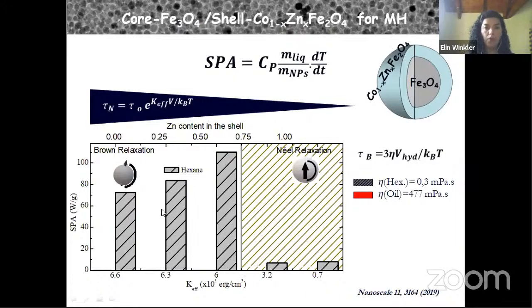So how can we prove that the heating of these three samples is produced by the Brown relaxation time? Our idea: if these samples relax by Brown relaxation, and we now fix the nanoparticles, we are going to inhibit that kind of relaxation. And we did that. We dispersed the nanoparticles in butter oil. The butter oil is solid at room temperature and presents a viscosity four orders of magnitude larger. When we did that, these three samples presented an important drop in the specific power absorption, which confirms that the relaxation mechanism of this system is the Brown relaxation mechanism.